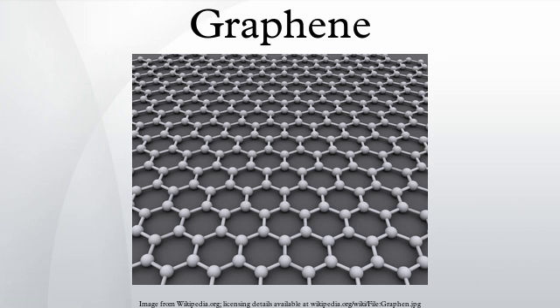Single-atom wave propagation: electron waves in graphene propagate within a single atom layer, making them sensitive to the proximity of other materials such as high-k dielectrics, superconductors and ferromagnets. Electron transport: experimental results from transport measurements show that graphene has a remarkably high electron mobility at room temperature, with reported values in excess of 15,000 cm² V⁻¹ s⁻¹. Additionally, the symmetry of the experimentally measured conductance indicates that hole and electron mobilities should be nearly the same.